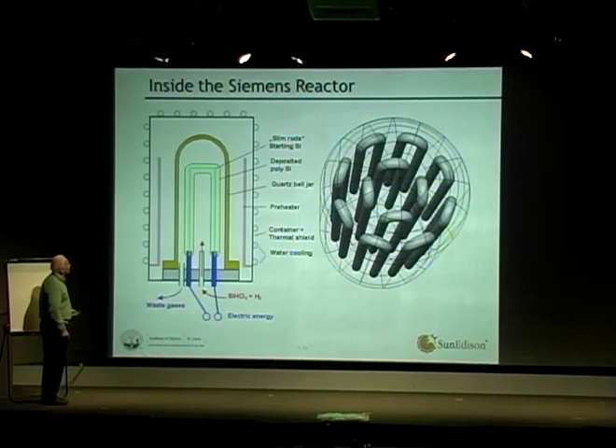It's thin, I guess 3/4 of an inch or something, an inch square. And they put two pieces up here and then put a piece across the top. Then you feed a high current through here and it heats up. As you heat it up and flow this stuff through, the trichlorosilane molecule breaks up and the silicon deposits onto the slim rod represented by this green line, and it grows out to the black line, so it becomes thick, as shown in this schematic here.